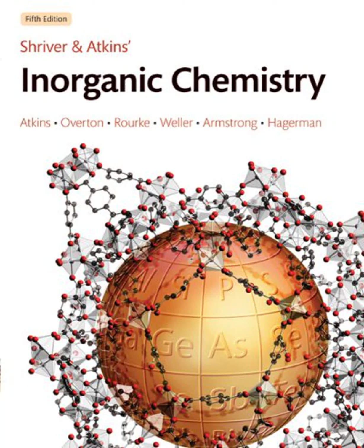You also mentioned earlier that only lithium forms a nitride and a carbide directly. That's right, reinforcing its uniqueness. Only lithium reacts directly with nitrogen gas to form lithium nitride, Li3N, a reddish solid. It's actually a good ionic conductor and has potential for hydrogen storage applications. And the carbide. Again, only lithium forms its carbide, Li2C2, directly from the elements. This contains the dicarbide anion.